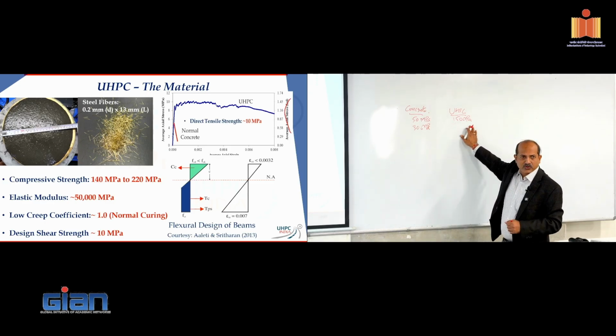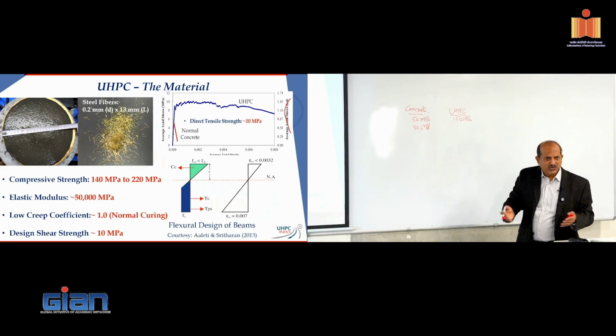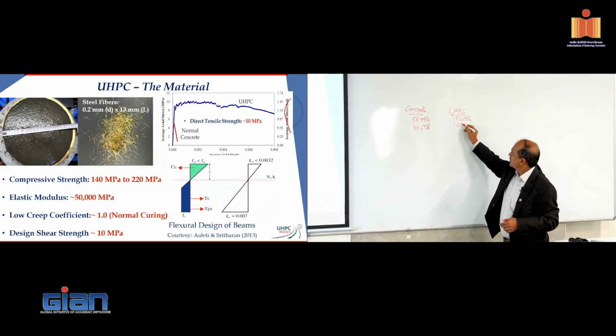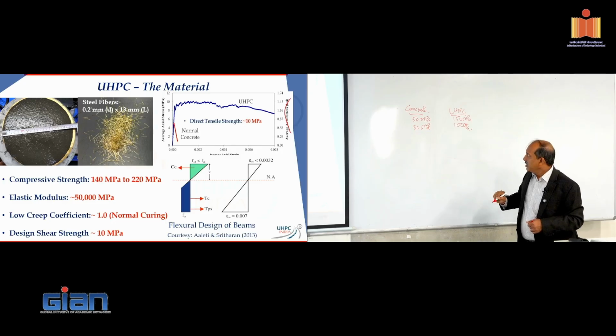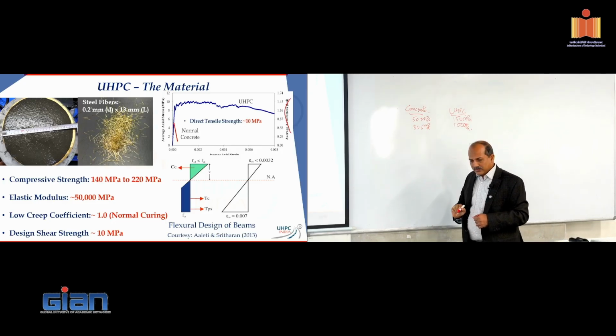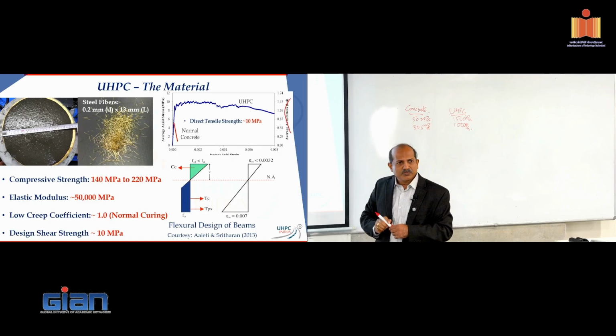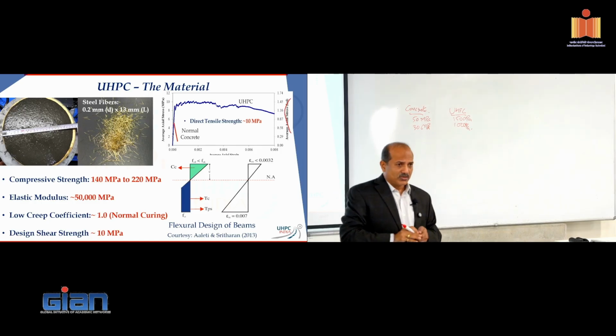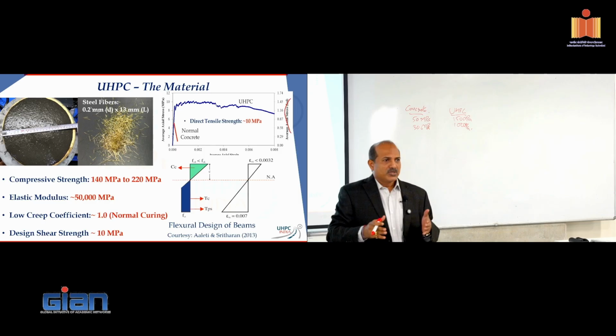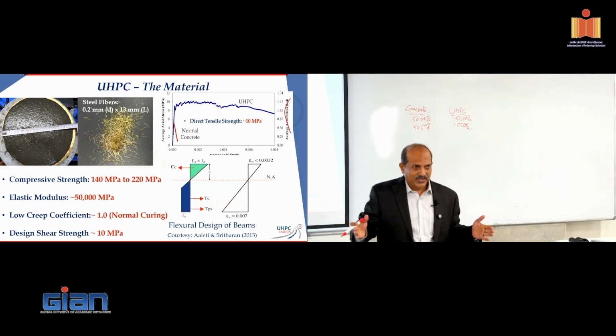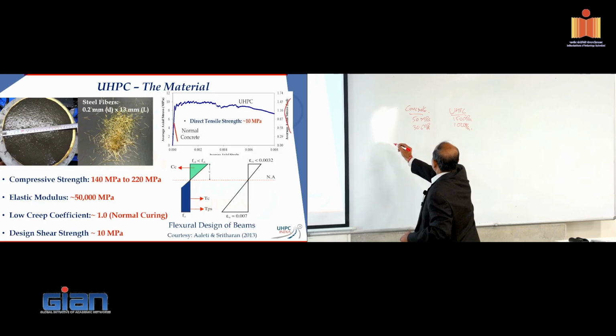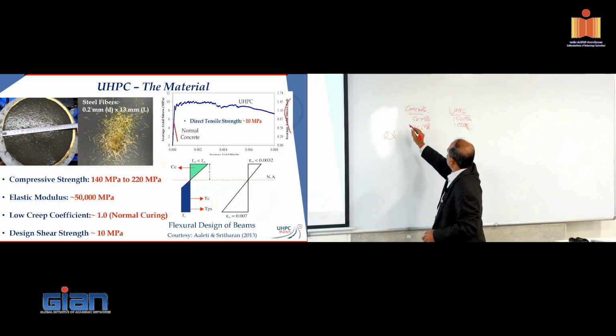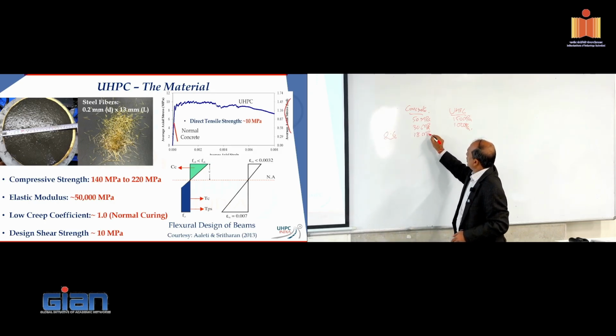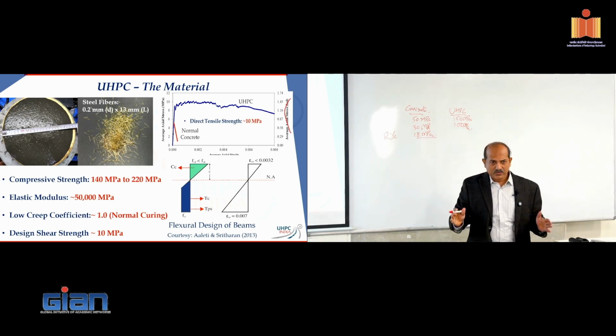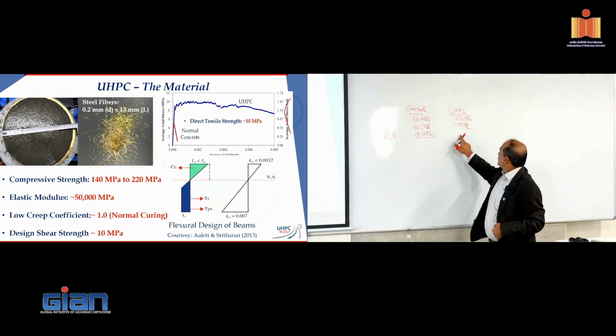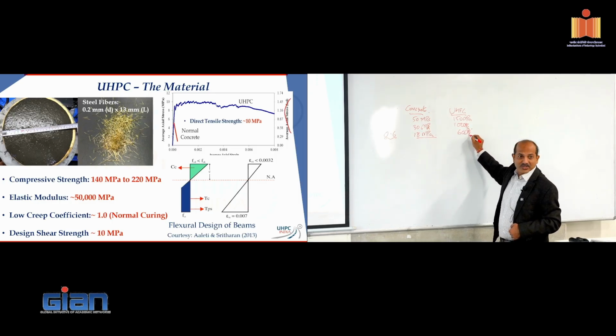Here, to take advantage of UHPC gains early strength, so in 3 days or something like that, you would have 100 MPa right over there. And when you have this, your initial pre-stressing stress that you put, probably about 60% at max, right? At max. So if you put 0.6 of this f'c, you're limited to about 18 MPa right at the initial phase. Whereas 0.6 of UHPC is 60 MPa.